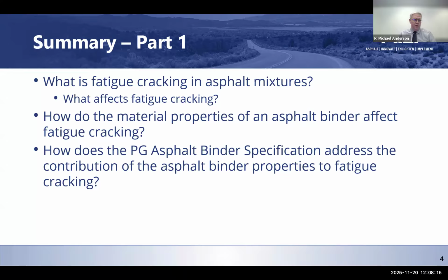Applied loading or stress also matters, and the strain that is applied into the asphalt layer, and that comes from the asphalt layer thickness. The thicker the pavement, the lower the strain is going to be at the bottom of the layer, and that helps extend the number of cycles to when a fatigue crack is going to occur.